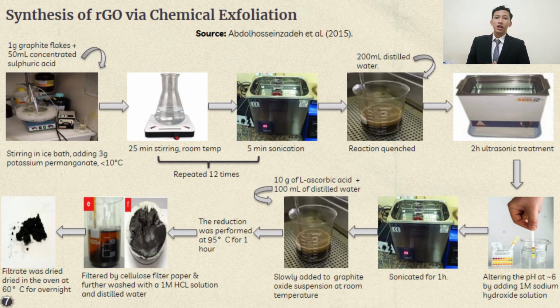For the synthesis of RGO by using the chemical exfoliation method, the process starts with the preparation of graphene oxide from graphite. This can be done by adding 1 gram of graphite flakes into 50 ml of concentrated sulfuric acid and stirred in an ice water bath. After that, 3 grams of potassium permanganate is added gradually while maintaining the temperature below 10 degrees Celsius.